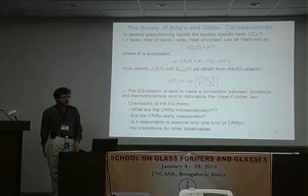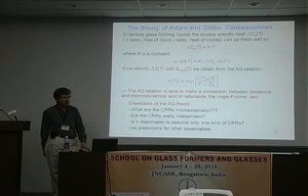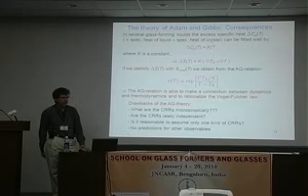And also, if you look at this simulation carefully, you don't necessarily see rotations all the time. You see them, but many things are better explained in terms of bond exchange. Some bonds are cut, and then a local part will become loose, so other bonds are formed. So one bond is cut, other bonds are formed in the immediate neighborhood, and that's the action. In a sense, it is localized. For instance, atoms would vibrate hundreds of times, and this bond cutting happens only once in 100 times. So in that sense, the atoms give the localized description of a small event controlling everything.